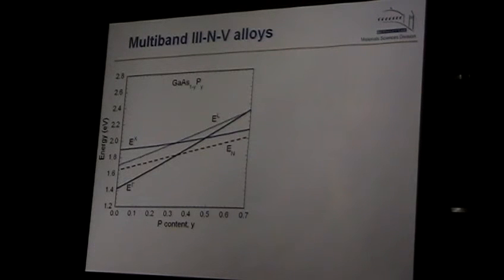So now we moved to gallium arsenide phosphide with nitrogen, because the other material had one significant problem. It's very difficult to dope N-type, and of course you cannot make solar cells if you don't have P and N type material. So in this case, in gallium arsenide, as you remember, the nitrogen level is above the conduction band edge. So it was not so good. We would like to have the nitrogen level below the conduction band edge.